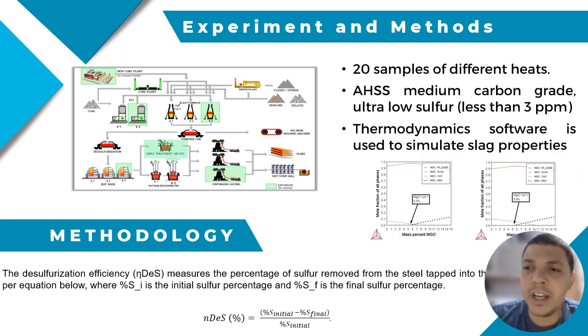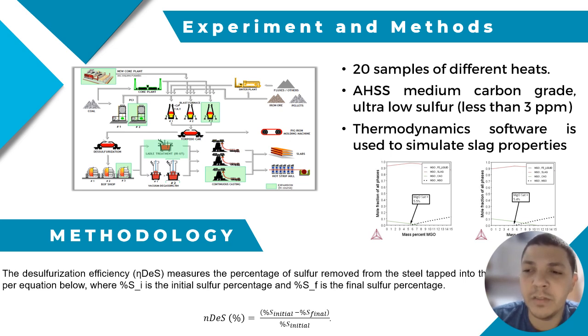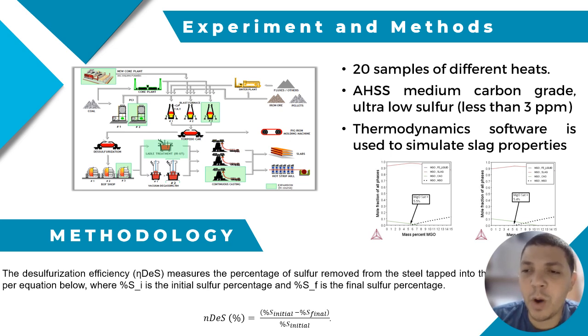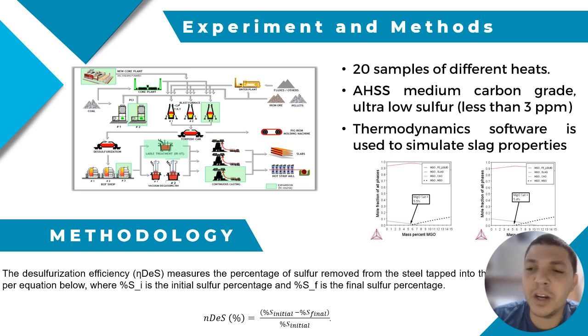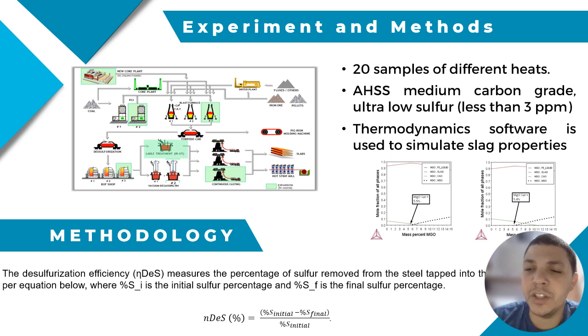For the experimental methods, we used 20 samples from different heats, all using real plant data. We chose an advanced high strength steel grade of ultra-low sulfur content — less than 3 ppm of sulfur — which means the wall of the ladle will be stressed by the reactions of high desulfurization. To simulate slag properties, Thermocalc and FactSage were used. We found that every heat has its own ideal MgO saturation based on the composition and slag properties.